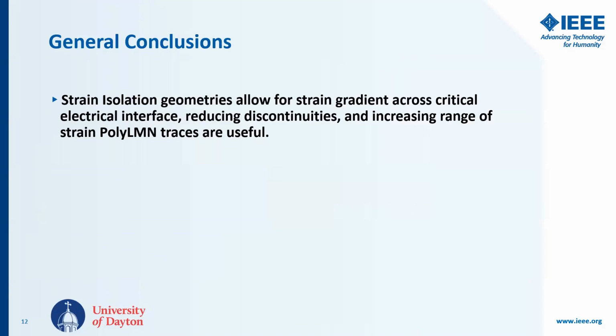And conclusions: strain isolation geometries allow for a strain gradient across critical electrical interfaces, reducing discontinuities and increasing the range of strain over which polymerized liquid metal traces are useful.